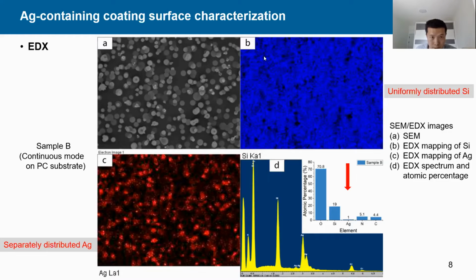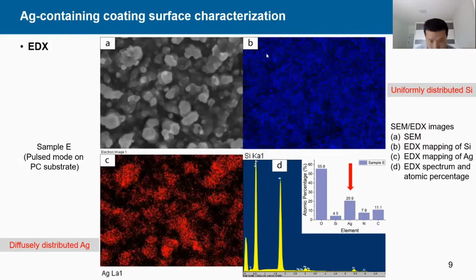So when we check sample E, the EDX map presents a quasi-uniform silicon element distribution, and the silicon and the silver element distribution has a diffuse distribution, which is quite different from sample B. And we can see also the silver content, which is almost 21%.